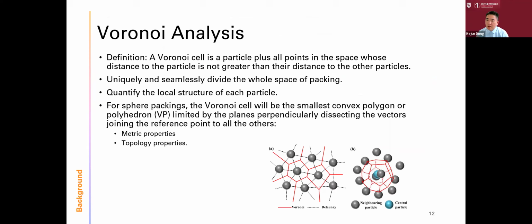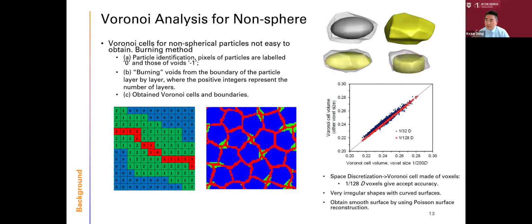Then if we want to look at pore size and local space metric properties, we can use a Voronoi analysis, right? Voronoi can tessellate the space in a unique way, and each particle can claim its local office with no overlap with other offices, in a mathematically precise way. For spherical particles, we can obtain the Voronoi polyhedron, and then analyze the local space of each particle according to the properties of this polyhedron. If we want to extend Voronoi to general non-spherical particles, we may need to use more numerical ways, because there is no easy way to get a polyhedron from a non-spherical particle that encloses its space.